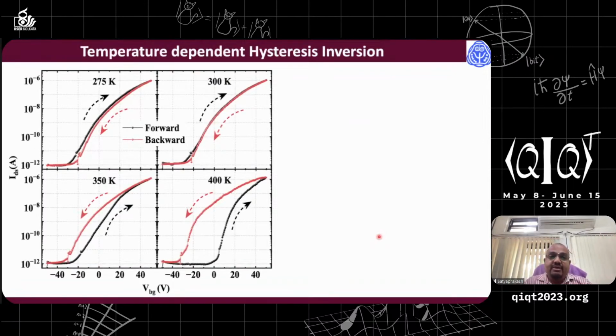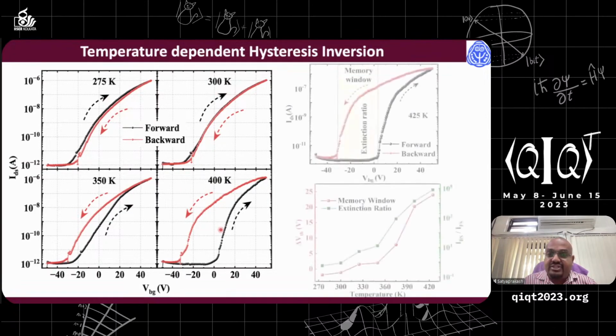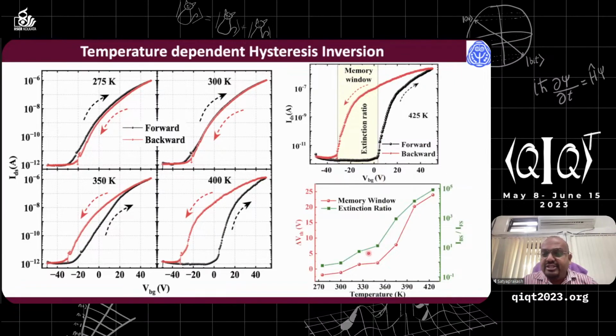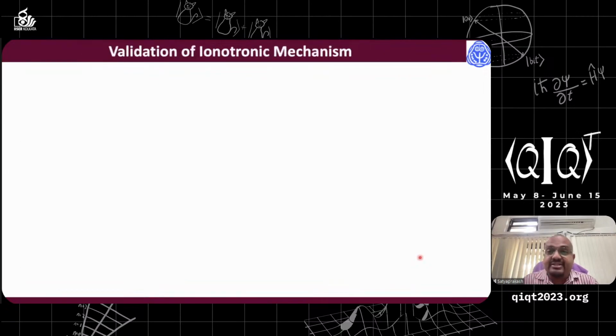And it has a direct effect on its hysteresis. You can see here, unlike the most samples that were shown, when you increase the temperature, it shows a wide range of hysteresis, correct? And this is the plot between the hysteresis width, which is basically the change in the voltage from here to here, and the current ratio. That means at 0 voltage, what is the ratio of the currents? You can see that both increase with increasing temperature. This is a very interesting one.